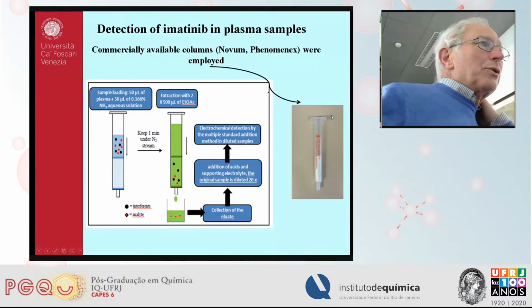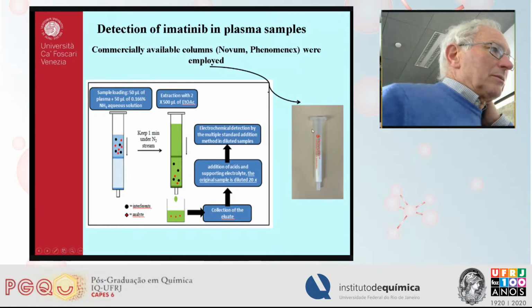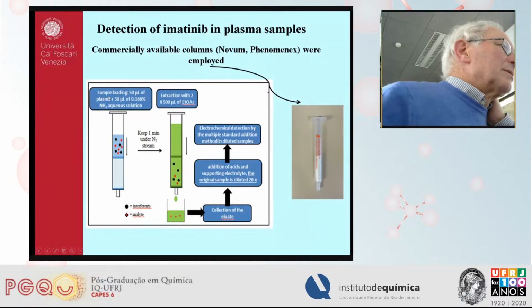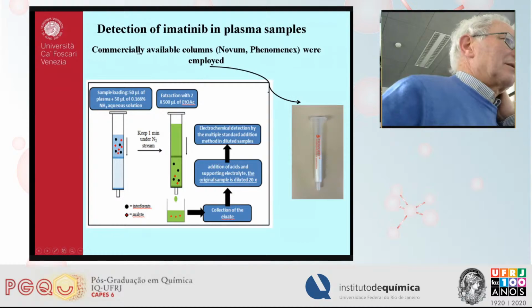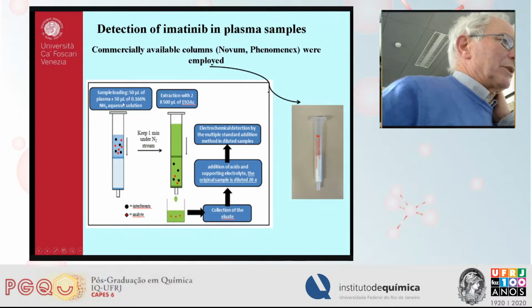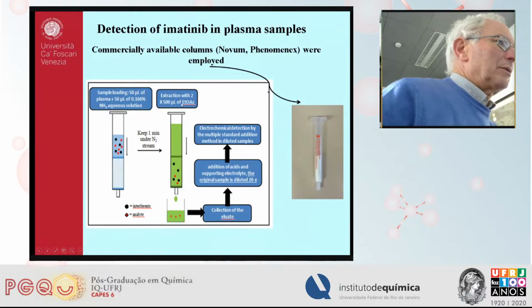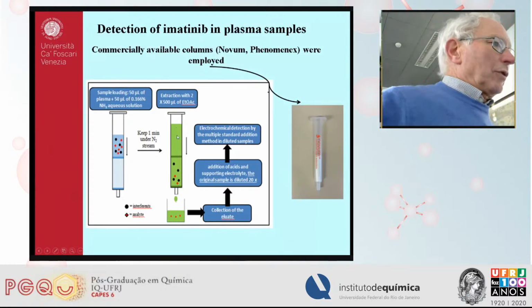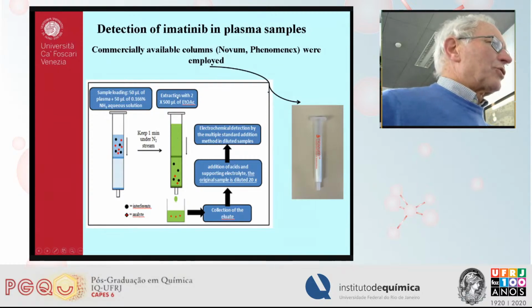So in this case, we used a different kind of column. A Novum from Phenomenex was employed. These are also commercially available. The extraction procedure was quite easy, and we could detect the imatinib concentration starting from about 50 microliters of plasma, much less than before. The imatinib was completely extracted from the plasma sample using ethyl acetate, the solvent, which is then used for the electrochemical measurement. So in this case, the procedure is much simpler.